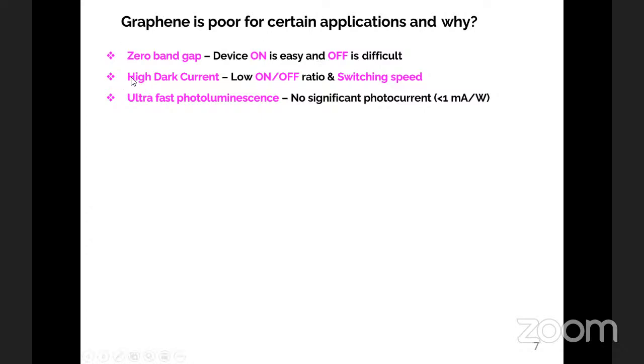And as we discussed before, graphene has high dark current, which means you will always have a high off current. So then there is no on, so the switching speed will be very, very low. And moreover, the other thing is the ultrafast photoluminescence. This phenomenon is in fact a disadvantage of graphene because graphene lacks a band gap.